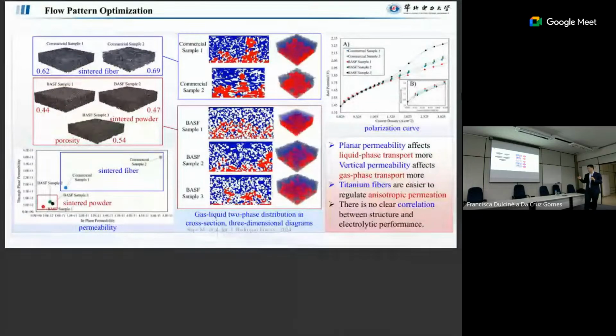Both work, but it's very difficult to say which one is better. When we check this bubble map, we cannot identify which one is okay. And when we check this curve, we can see that this one with the sintered powder is better. But in my opinion, you can find a lot of this kind of experiment in the literature. If you make this comparison to say which one is better, it's difficult. Even for the PTL itself, you cannot identify if it's good for mass transport or not, because it needs to work together with the channel system. When they're compatible, then it's good.